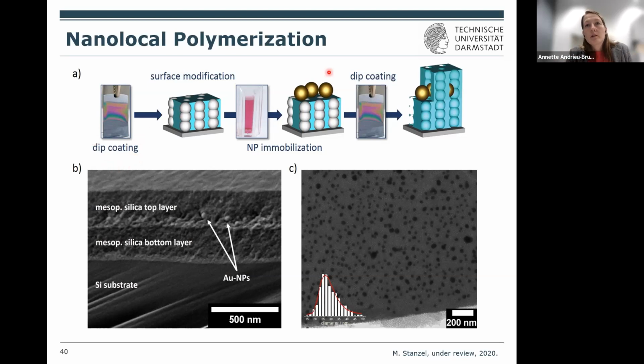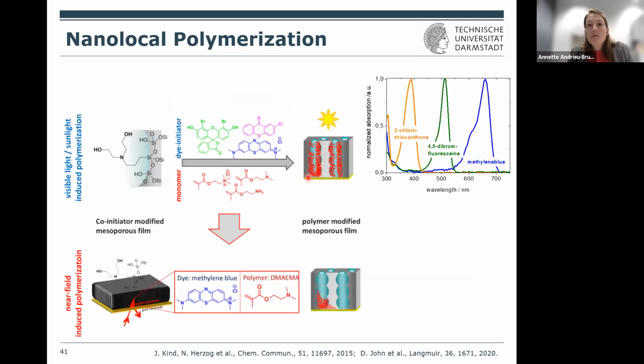So what we did is incorporate these metal nanoparticles between different mesoporous layers. This is what you see here nicely in the TEM images and as well in the cross section. And then you have still one challenge, because these plasmons, doesn't matter if they are on planar surfaces or on particles, are usually in a wavelength range that is not compatible with everything that you know from classical light-induced polymerization. So you need a polymerization that matches this plasmon wavelength, which is usually, let's say, 400 nanometers or higher, and higher is more frequent.